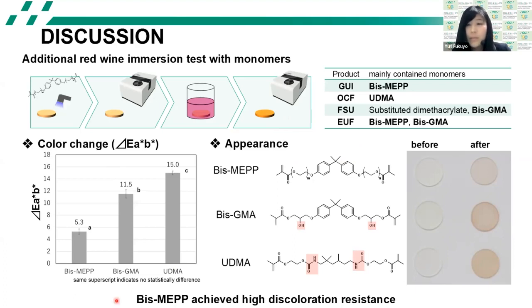BIS-MEPP showed significantly less discoloration compared to BIS-GMA and UDMA. So focusing on their structures here, BIS-GMA and UDMA contain hydrophilic functional groups, while BIS-MEPP doesn't. Therefore, it's considered that BIS-MEPP achieved high discoloration resistance because of its structure.